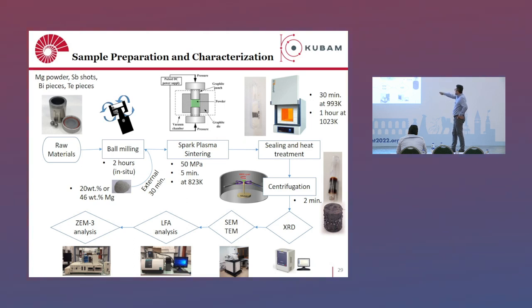You do sintering with spark plasma sintering at certain conditions to make this bulk material. And then we seal this bulk material in a quartz ampule under protective atmosphere, because if you put it in an oven, it will be oxidized. To avoid that, we put it in a quartz tube and then put this in an oven. We did a quick centrifugation. You can see that the magnesium in the molten state just comes out from the bulk piece, and you can clean this and investigate the microstructure.